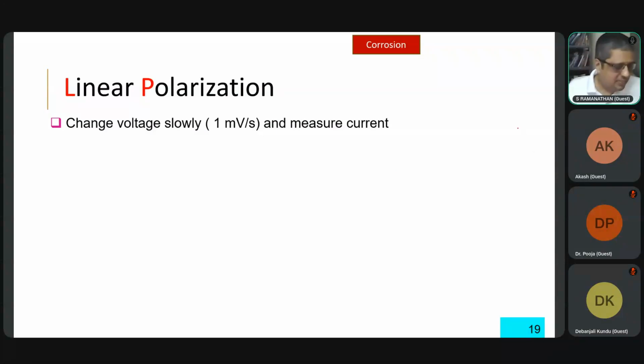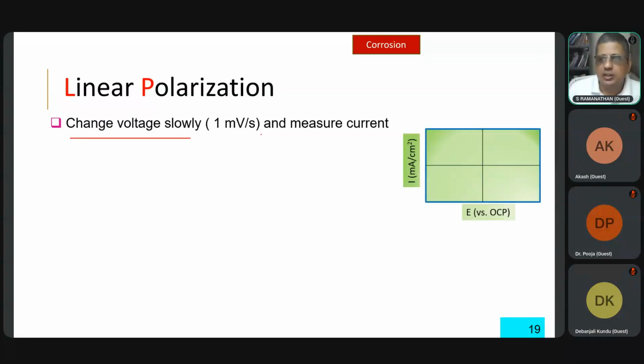There are some techniques which are specific to corrosion. One is called linear polarization. This is easy to do. What we do is we change the voltage slowly and measure the current. When I say change the voltage, we first measure the open circuit potential. That is, we just put the material and measure the voltage, whatever happens naturally without any current. Then we lower the voltage a little, 10 millivolt, 20 millivolt, and then slowly change the voltage and monitor the current. So 10 or 20 millivolts around the OCP, and then we slowly change and monitor.